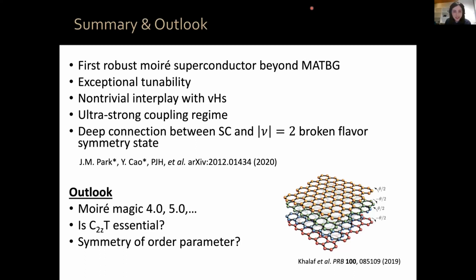Yep, thanks a lot. And there's another question in the chat by Stefan Roche, which is, why don't we see fractional quantum Hall effect in these systems if they are clean enough and we look at low enough temperature and high magnetic field? Mm-hmm. The flat bands have much higher effective mass, and therefore the mobility of the systems is substantially lower than regular monolayer graphene or regular bilayer graphene. So from that point of view already, you would expect it to be less likely that you would see fractional quantum Hall effect under the same conditions.